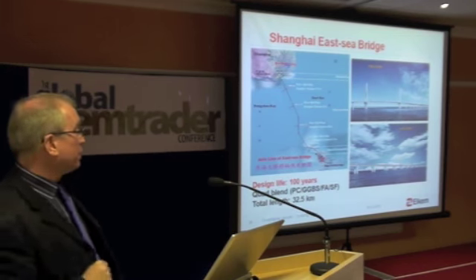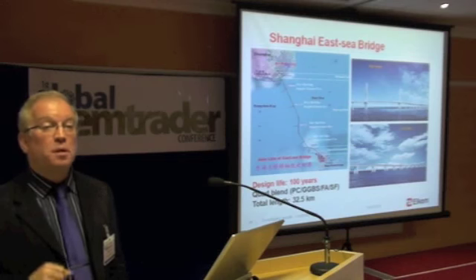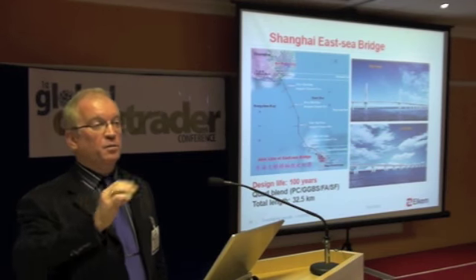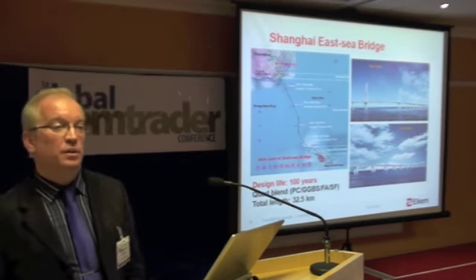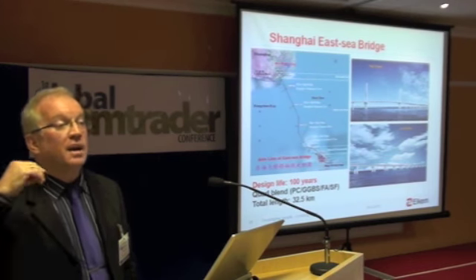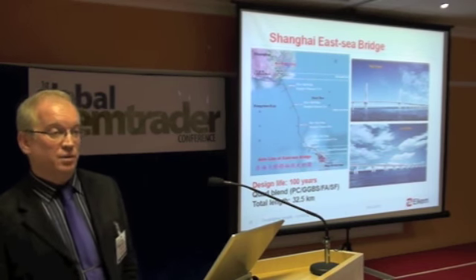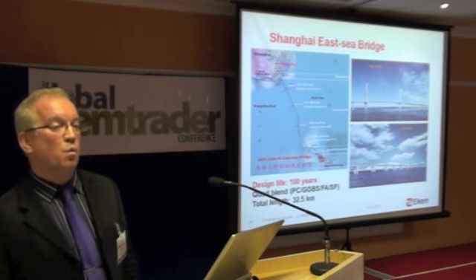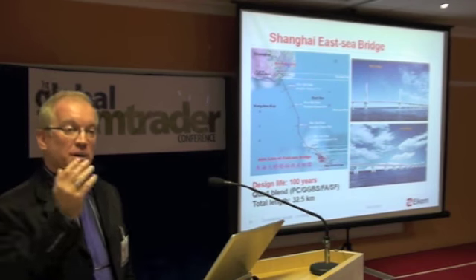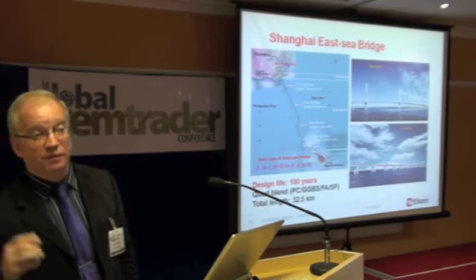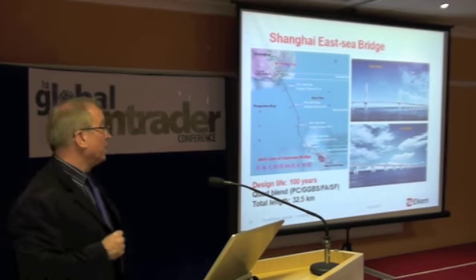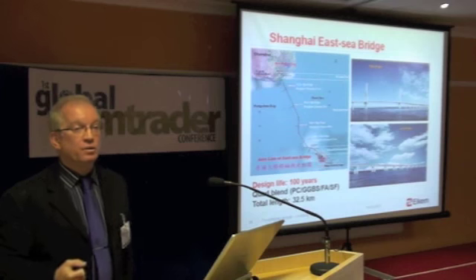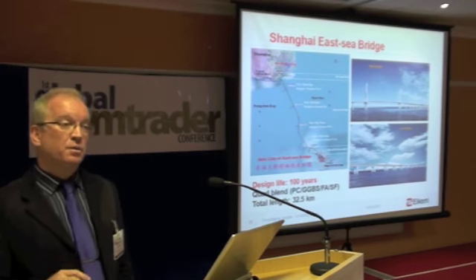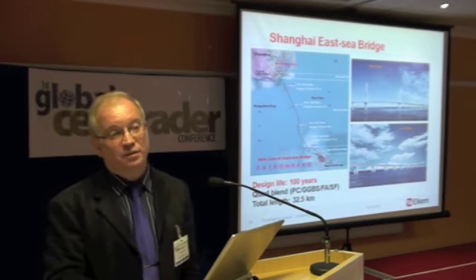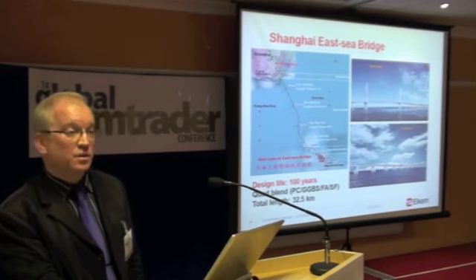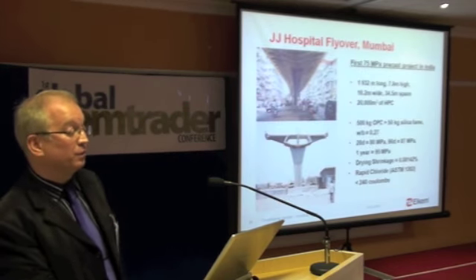Quad blends, all 4, OPC, slag, fly ash and microsilica. This particular bridge used 2 mixes, pre-blended. They were blended off-site, they were shipped to the concrete production units, 2 silos, that's all they needed on site. One silo held one, the other silo held the other. They made a 35 megapascal or a 50 megapascal. Incredible durability required, 100 years in that environment. 32.5 kilometers, they built it in less than 3 years. That's the sort of speed and turnaround we can do.